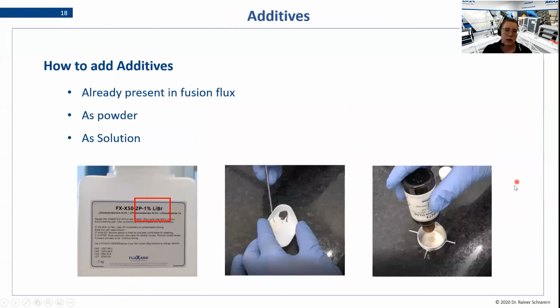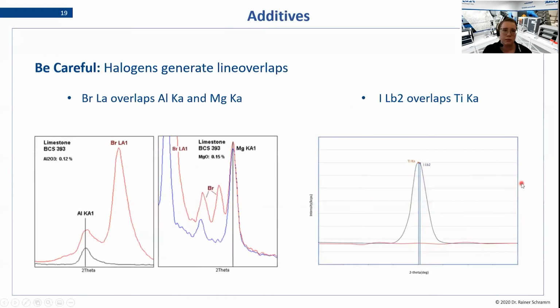How are we adding additives? Additives can be already present in the flux, and they can be added as a powder or as a solution just by adding small drops. So this all sounds very nice. Our beads are not sticking and breaking, but still we can have some trouble later. So be careful, because these halogens we are using generate line overlaps in your measurement later. So be careful of that.